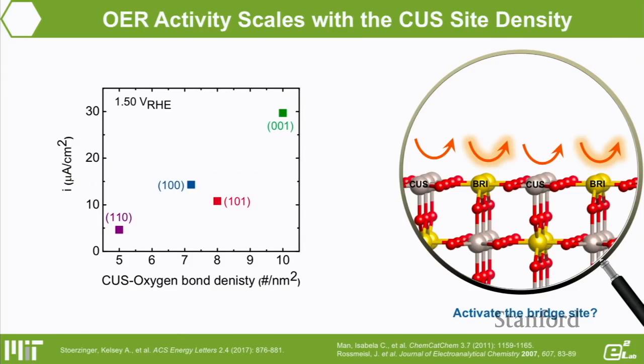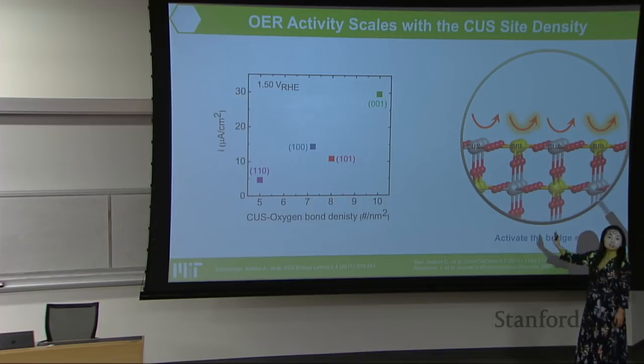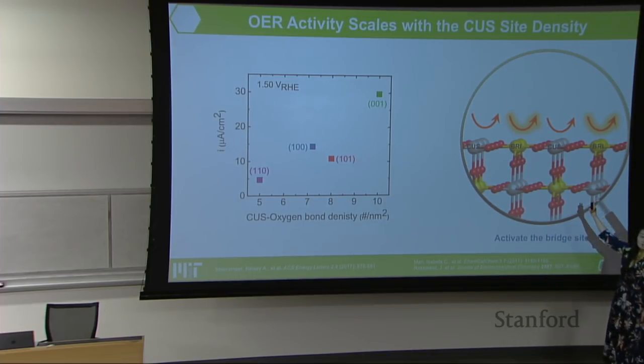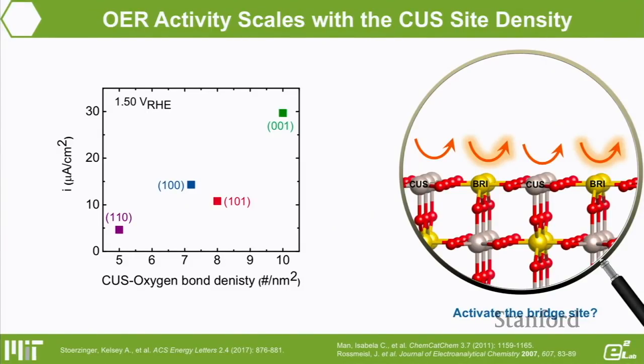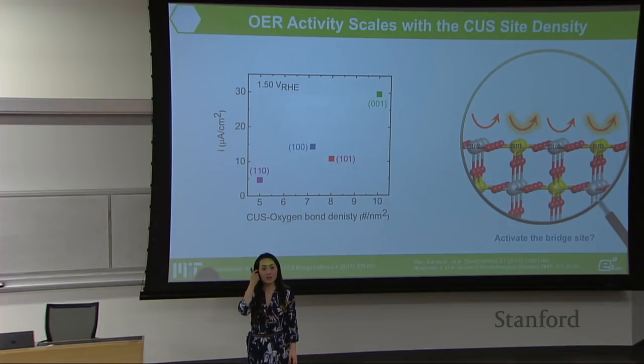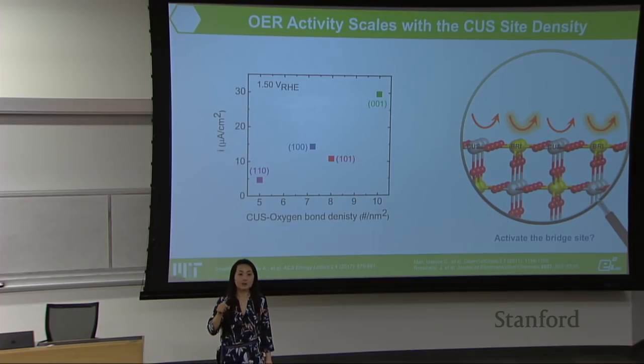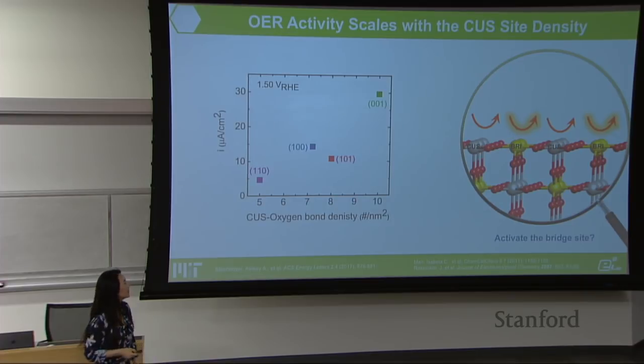And what we find is that you can correlate the oxygen evolution activity to the Cus oxygen bond density. As you increase the Cus oxygen bond density, you can change the activity by up to an order of magnitude. So this is a very interesting picture: the Cus site is active, the bridge site is not active. So the question would be, can we activate the bridge site, either through something on the solution side or through the surface via substitution? That's the work we're currently doing, through machine learning of various substituted surfaces to activate both the bridge and the Cus site, because we know what the energetics for the reaction intermediates need to be. We need to know the density of states for each site required for optimum oxygen evolution reactions.